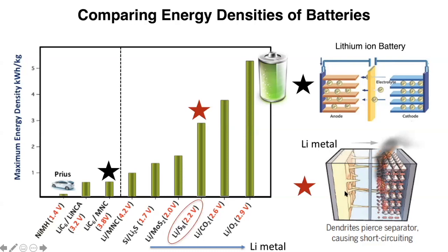But the thing with lithium metal is that, and also to get this high energy density, you notice the unit is per kilogram. So this per kilogram includes the weight of everything in this battery, including the weight of the electrode and the current collector, which is typically made of copper, but copper is very thick. So we are also trying to basically not use any copper and have lithium metal directly deposited to remove this weight. And then the weight of separator, weight of electrolyte, weight of the cathode, all of them are used in this equation to calculate the energy density.